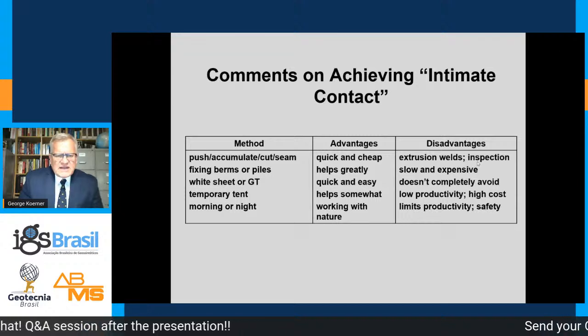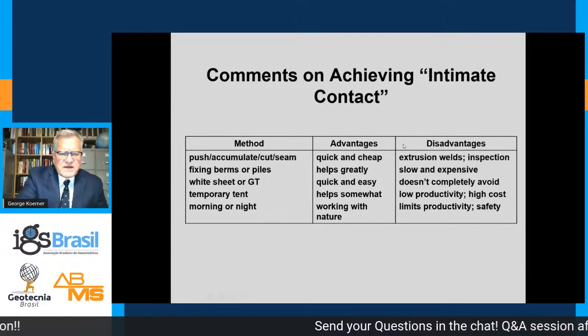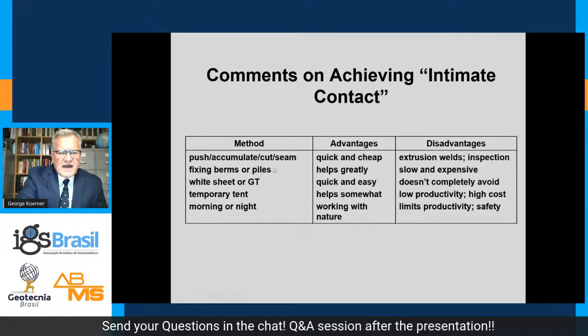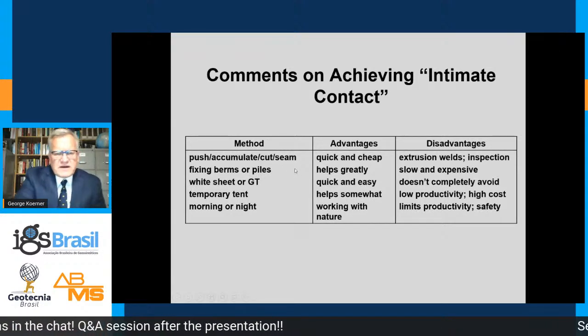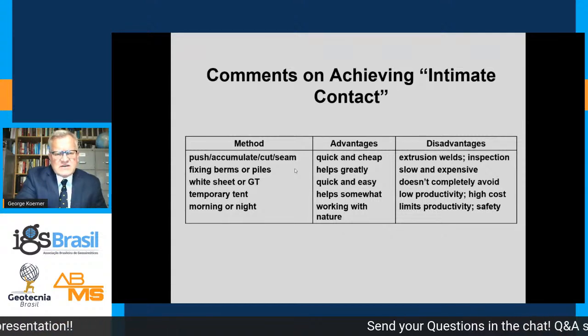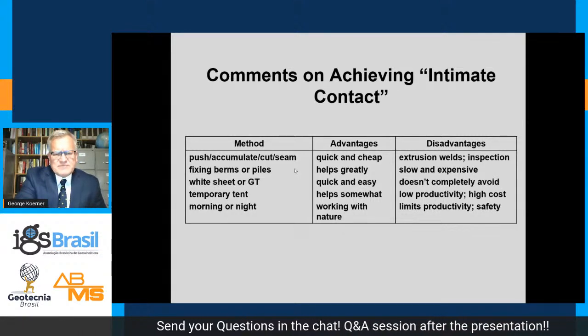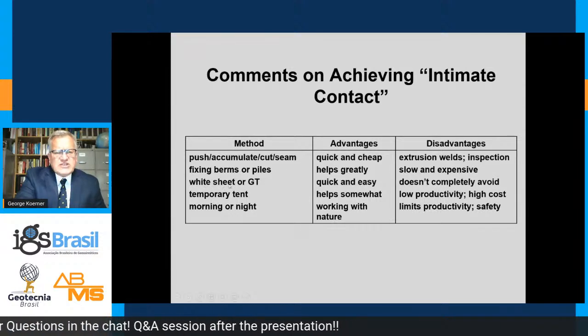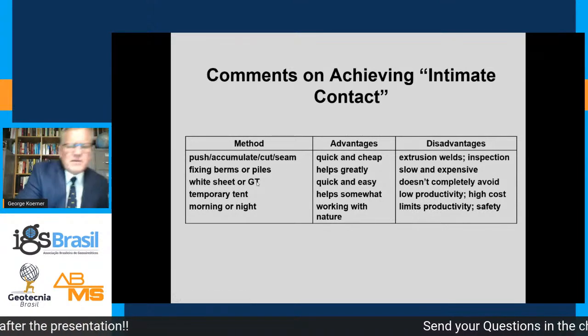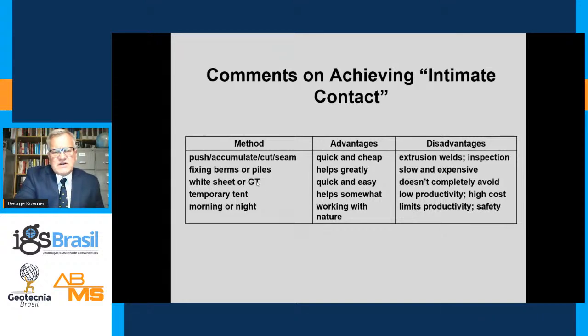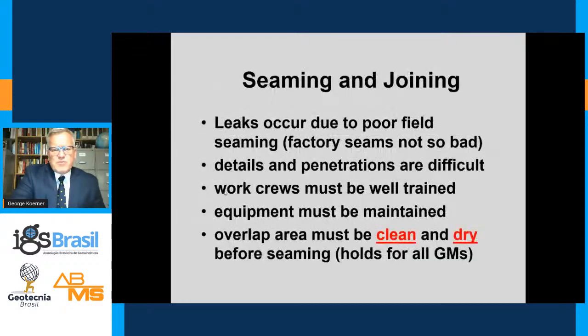Certainly that push, accumulate, cut, and seam, it's labor intensive, but it works. Fixing berms and piles. This is available over in Europe. A company by the name of Schicketanz has certainly championed this with thick geomembranes in Germany and Austria. White sheet and white and light colored geotextiles help. If you decrease the surface temperature of these membranes, you certainly have less wrinkling. If you can control the environment either with tenting or support structures, or do work in the morning or late at night, this is certainly proactive and will help you in regards to intimate contact, which is extremely important.